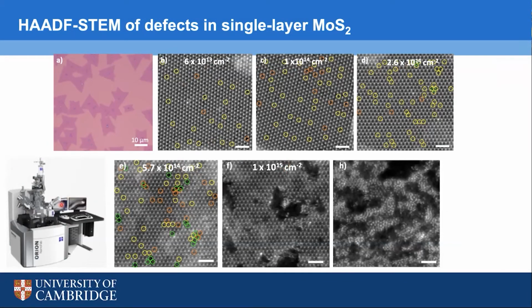The good thing about the helium-ion beam, say compared to an argon-ion beam, is that it is quite gentle, in the sense that it's able to remove sulfur atoms without destroying the entire structure. That is, we can remove the sulfur atoms one by one with a helium-ion beam while maintaining the overall MoS2 nanosheet structure.